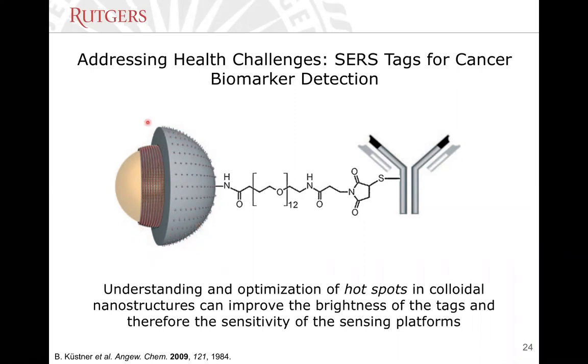Then you can coat the nanoparticle with the reporters, either with silica, or if you don't want to use silica, just with polyethylene glycol. The important part is that the outermost terminus of the polyethylene glycol needs to be functionalized to carry a targeting moiety. This can be an antibody that targets a protein or proteic biomarker, but you can have aptamers, which in our group we prefer. Aptamers are oligonucleotides based on RNA or DNA that fold in specific hairpin conformations and are designed to very selectively and strongly bind to their specific targets. And in some cases, they behave even better than antibodies.